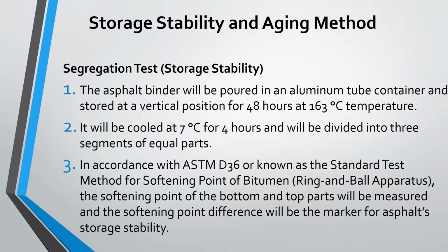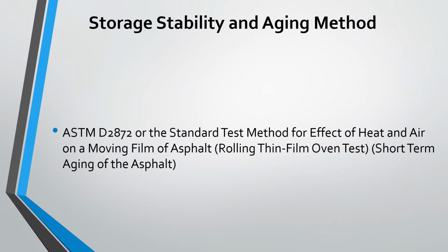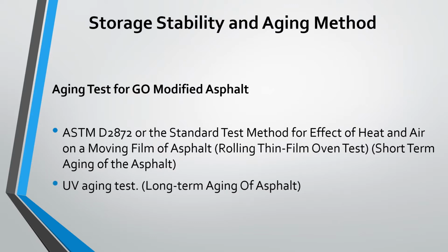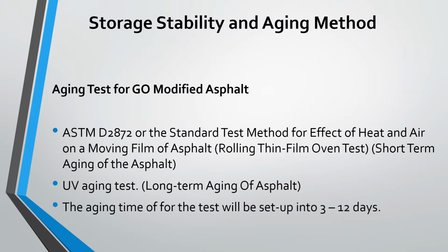In order to assess the aging of the GO-modified asphalt, ASTM D2872, or the standard test method for effect of heat and air on a moving film of asphalt, also known as the rolling thin film oven test, will be used to assess the short-term aging of the asphalt. On the other hand, UV aging tests will be used to assess the long-term aging of the asphalt. The aging time of the test will be set from 3 to 12 days.